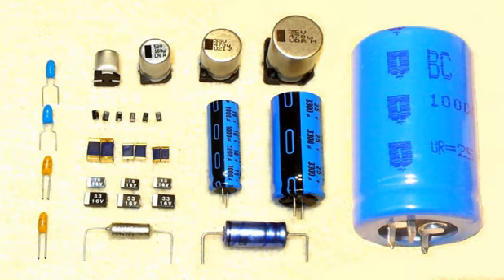Performance after storage. All electrolytic capacitors are aged during manufacturing by applying rated voltage at high temperature for a sufficient time to repair all cracks and weaknesses that may have occurred during production. However, a particular problem with non-solid aluminum models may occur after storage or unpowered periods. Chemical processes, corrosion, can weaken the oxide layer, which may lead to a higher leakage current. Most modern electrolytic systems are chemically inert and without corrosion problems, even after storage times of 2 years or longer.